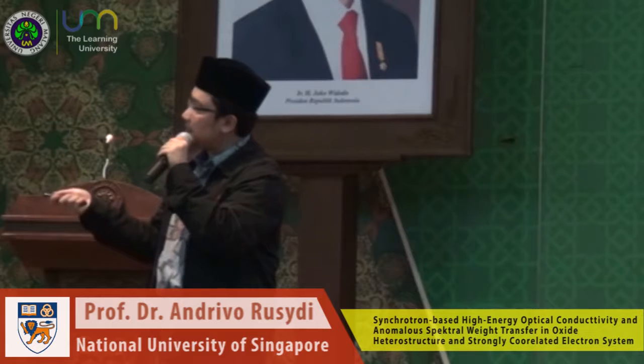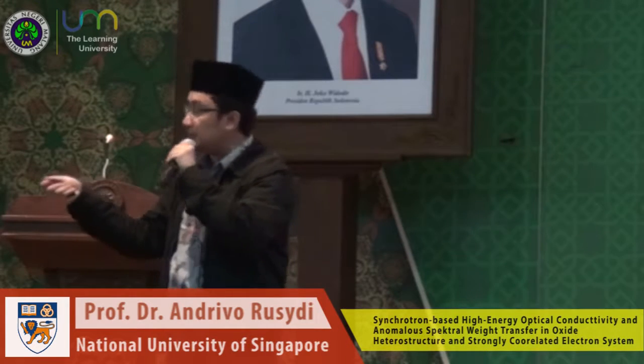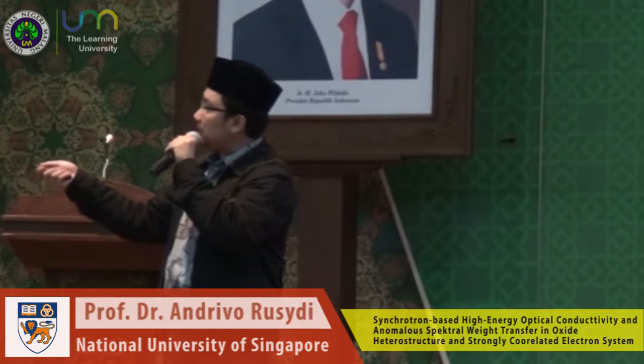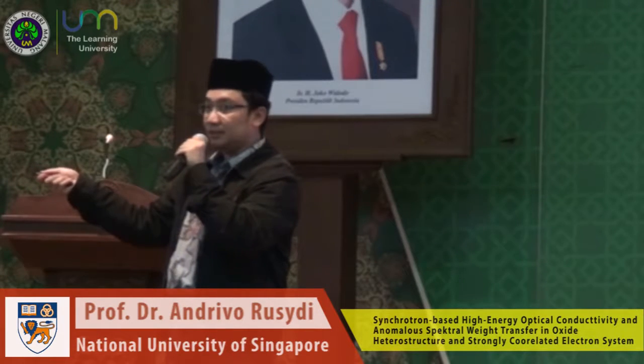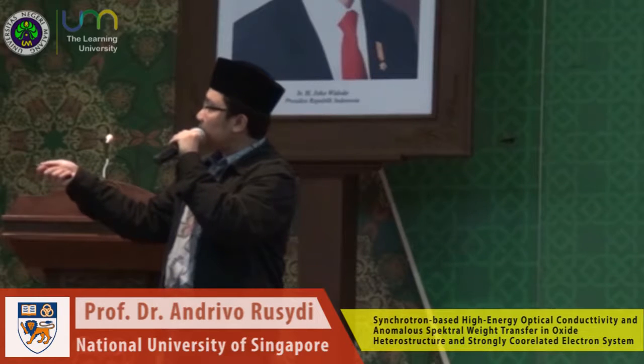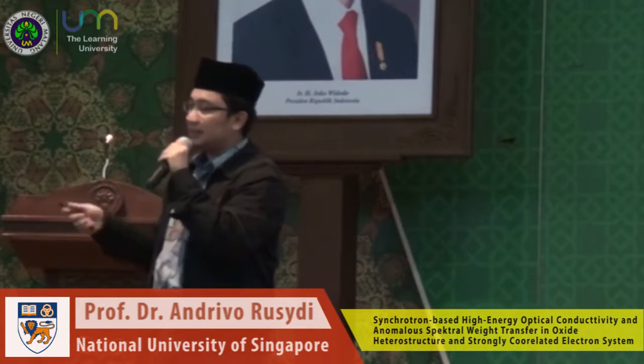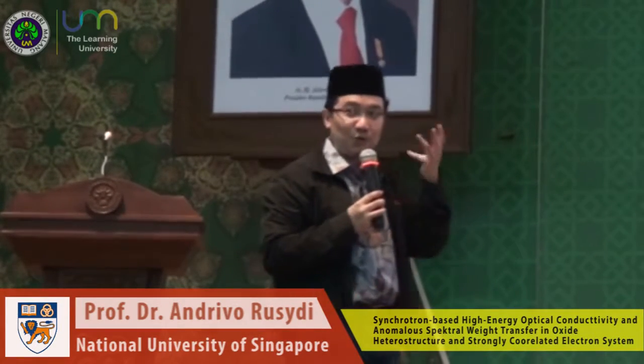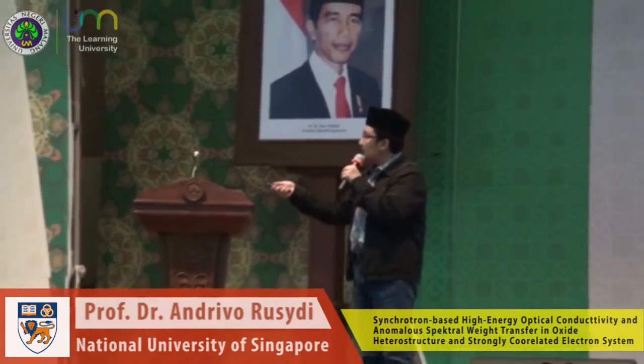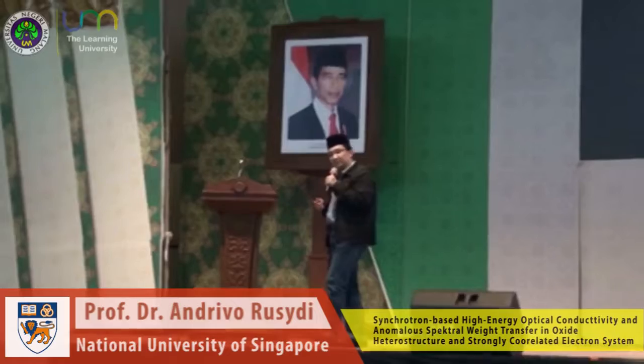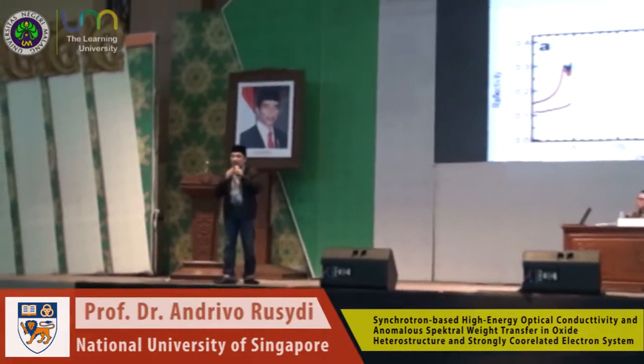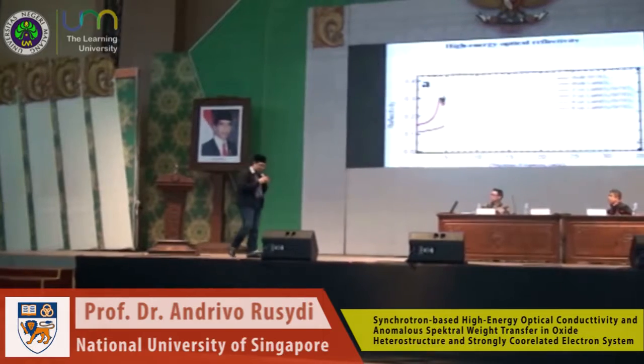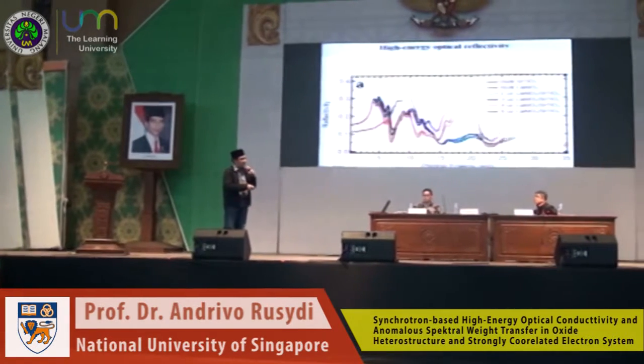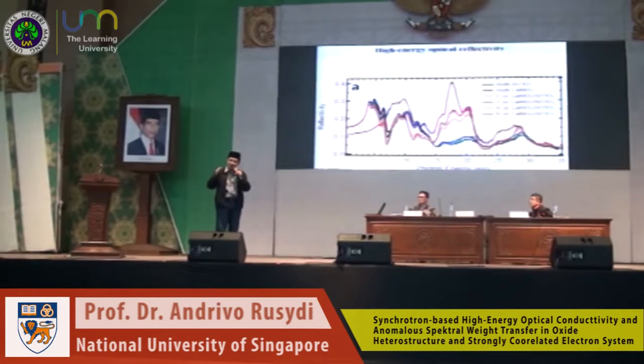And remember once again, if you do a regular experiment without the synchrotron, it's very hard to distinguish between 2 and 3 unit cell and 4 and 6 unit cell. Remember, what you want to understand is that 2 and 3 unit cell are insulating material, and 4 and 6 are a metal. So we want to understand how to explain why these are insulators and these are metals. Right? But then you scan the energy. You do the reflectance measurement all the way, and you scan up to 35 electron volts. It's a huge number there.